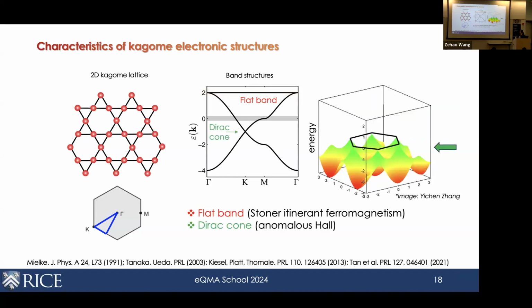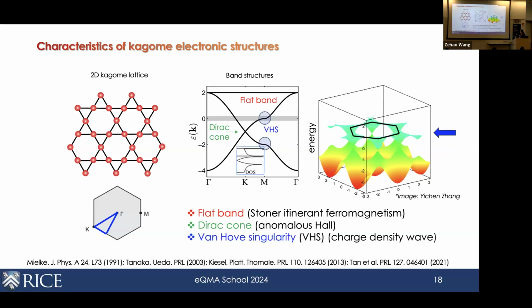Second, there is a pair of these saddle points. A saddle point means that the band dispersion is hole-like along one direction and electron-like along the orthogonal direction. And strictly in 2D, this will give rise to a Van Hove singularity with a divergent density of states. And so for Kagome systems, the second part is the Dirac point. If you lower your chemical potential to the Dirac point, you would get Dirac points at the K point in the Brillouin zone. If you have spin-orbit coupling, this will give rise to finite Berry curvature and also anomalous Hall. The third feature is this pair of Van Hove singularities. Of course, if you tune your chemical potential to be at the Van Hove singularity, this will give rise to this divergent density of states.